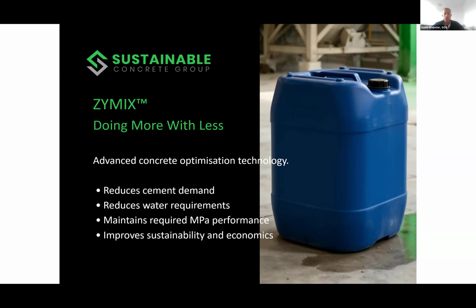Zymix, as I mentioned before, uses roughly 15 to 20% in the higher mixed designs. If we're talking 40, 50 MPa mixed designs, then it's upwards of a 20% savings. The product is less expensive than cement, and it is still obviously then achieving the desired MPa results. It also uses 7% less water, which again is another ESG or environmental compliance tick.